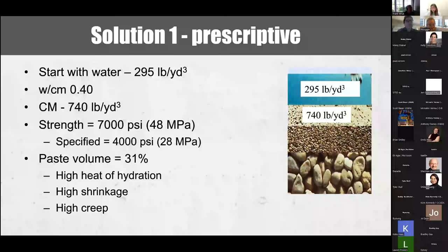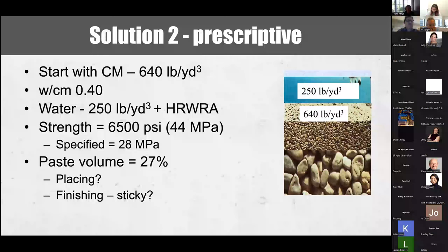Another option is to start with the maximum cementitious materials content and use the same water to cementitious material ratio to get the water content. In this case, a water reducer will be required to achieve the slump. The strength of this mix will be similar to the previous option because it is at the same water to cement ratio. The paste volume is lower, but it is likely this mixture might have problems with placing and finishing because of a likely higher dosage of admixtures.